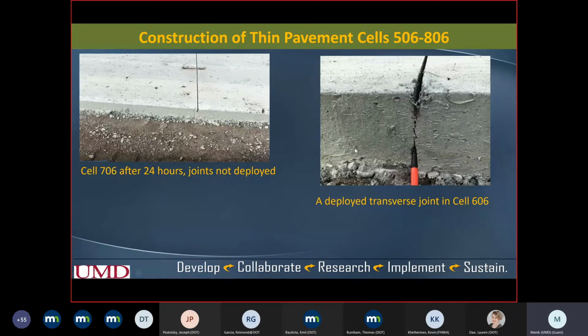These are some pictures I took on the day of the construction of cell 806, but these pictures are not for 806. As you can understand, 806 was fresh concrete at that time. So this is from 706. 706 had 8 pounds per cubic yard of fiber, and this is 24 hours after the paving. The joint, you can see, is sawed but not deployed.